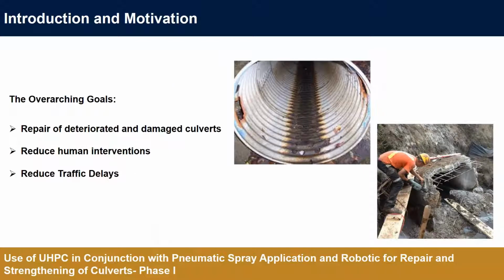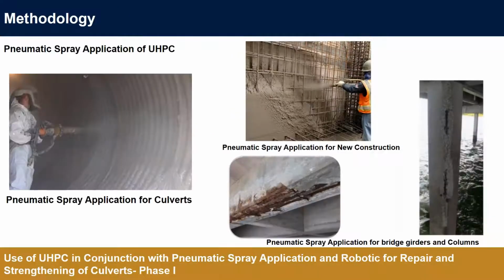First of all, the overarching goal here, as you can see on the right side of this screen, is that in some cases we have corrosion in steel pipes for culverts, and also some serious damage to concrete culverts. So the overarching goal of this study is to repair deteriorated and damaged culverts. As much as we can, by some robotic advancement, we can reduce human intervention because it's a very tight space in most cases, and also reduce traffic delays in the embankments.